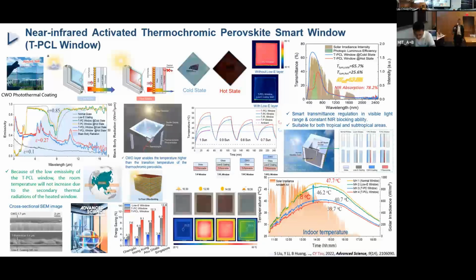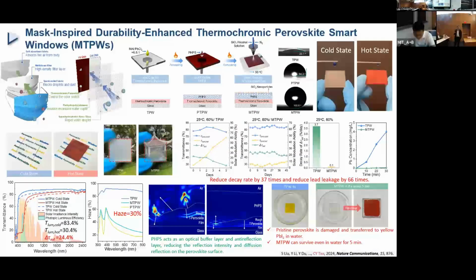But for this kind of window, no matter whether you are talking about perovskite smart windows or perovskite solar cells, another issue is usually the stability and lifespan. So how do we solve it? Typically for this 3D perovskite material, the lifespan is around a couple of days, two or three days, and after that the thermochromic effect disappears. To solve this problem, our team recently published in Nature Communications a solution inspired by the face mask that we wore every day during the pandemic period. The face mask has three layers. The outer layer is to repel the bacteria and allow a certain amount of air into our lungs.